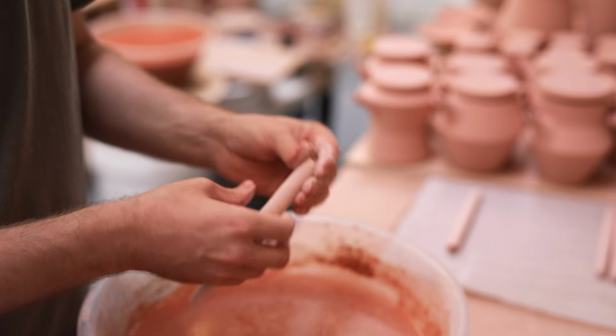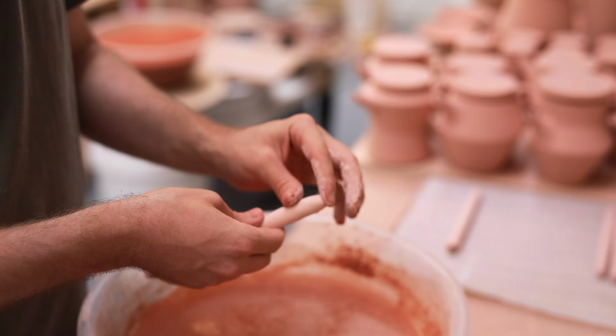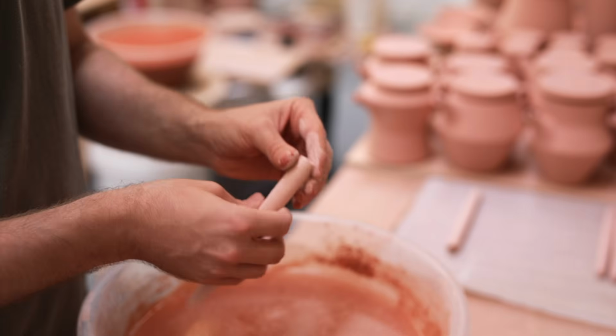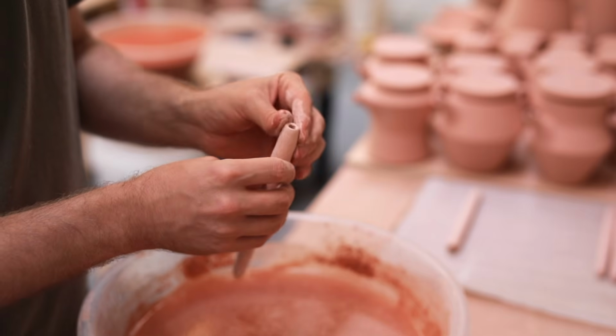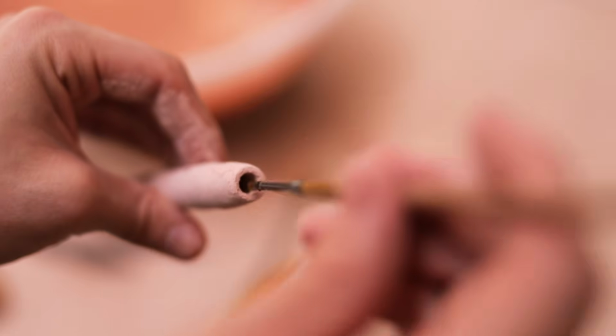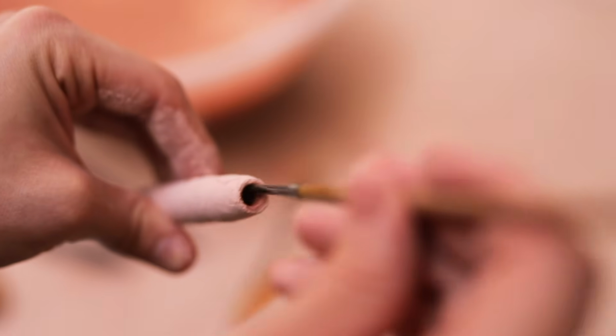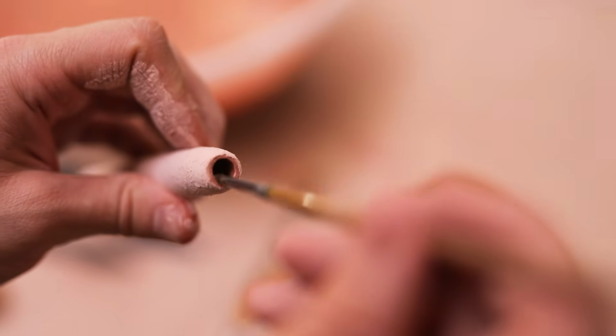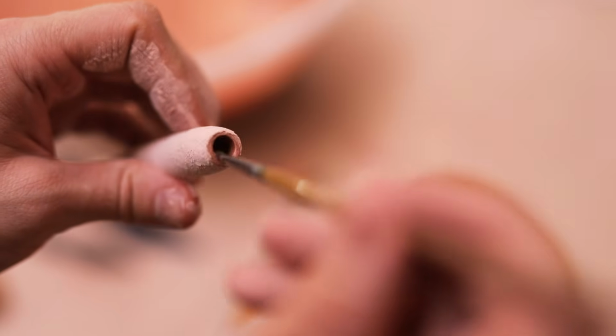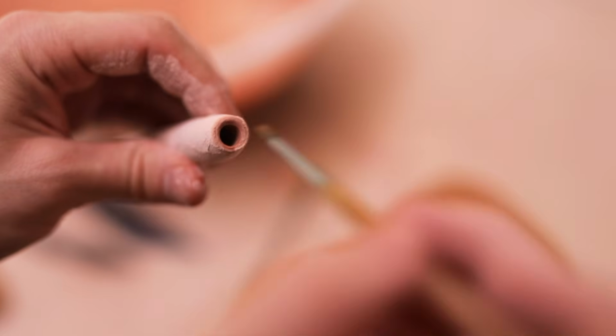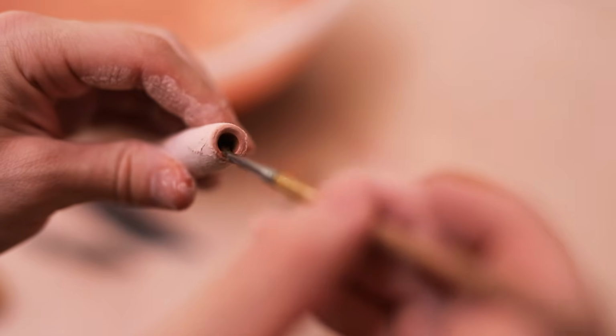As I work, you'll notice beneath me is a basin of water which collects all the excess glaze that comes off during this process. I then use a small wetted paintbrush to clean off the inside and also fettle away about 1 millimeter or 2 of glaze from around the hole, just so there's no risk of the glaze on the outside rolling inward and sticking to the metal during the firing.